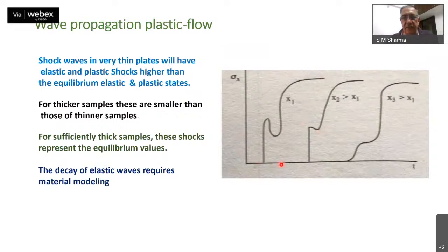Suppose you do experiments with a very thin sample, what you're going to see is a large jump here, which we showed as the instantaneous metastable state. Then it is going to relax back and eventually slowly go into its equilibrium value. If we took a thicker plate, this relaxation won't be that much, so it will go and slightly relax. And if you have still thicker plates, it will go to what we call the stable equilibrium phase. So this is the first jump it will take, and this is the final state it will occupy. So this represents the Hugoniot elastic limit, and then this is the final transition stress. It will take this.